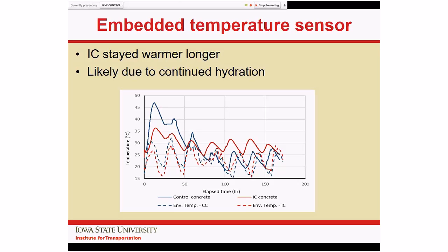We also buried thermocouples into the concrete, and what it's basically telling us is the dotted lines here are the environmental temperature, so the daily up and down. The control concrete did get pretty hot. The internally cured concrete did not go through that same spike, and again, I think that's largely a function of the higher slag content. But what's interesting is that over time, the internal curing kept going.